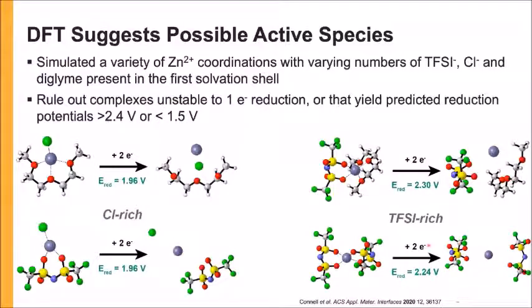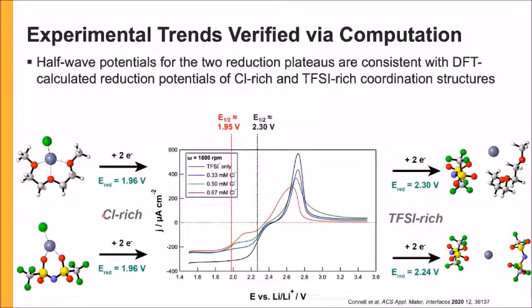And what we see is that the trend predicted by DFT matches very nicely with what we see in the experimental results, where the TFSI-rich coordinations predict reduction onset positive of that with the chloride-rich coordinations. Not only that, these structures actually match very well with the experimentally observed thermodynamic reduction potentials that we see in the voltammetry. And so what this says is that this idea of this cooperative effect between TFSI and chloride leading to the overall more reversible electrochemistry does appear, in fact, to be a reasonable hypothesis.